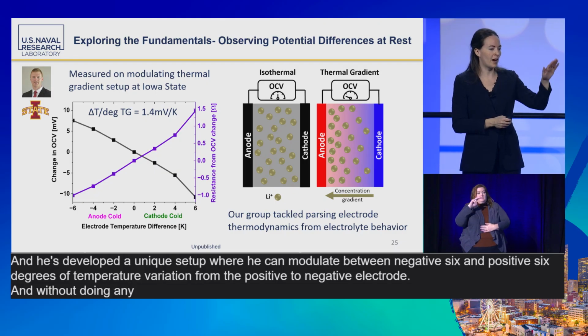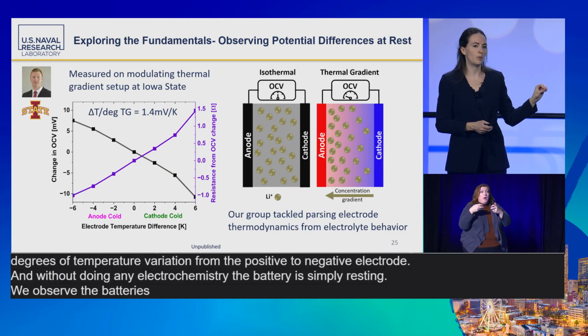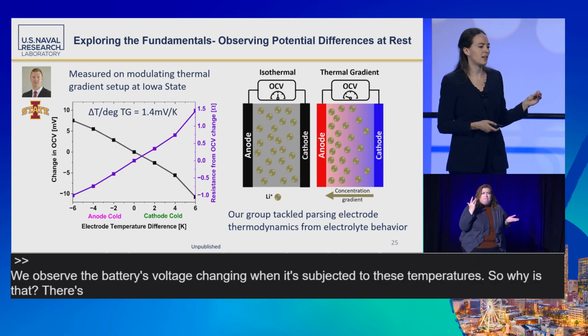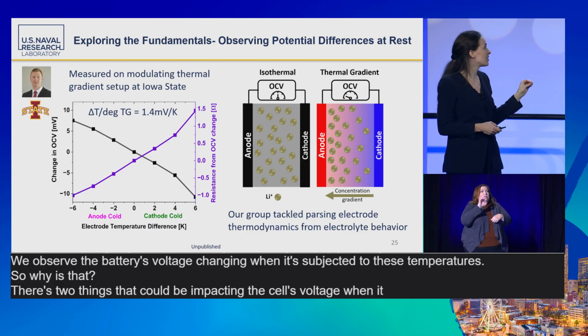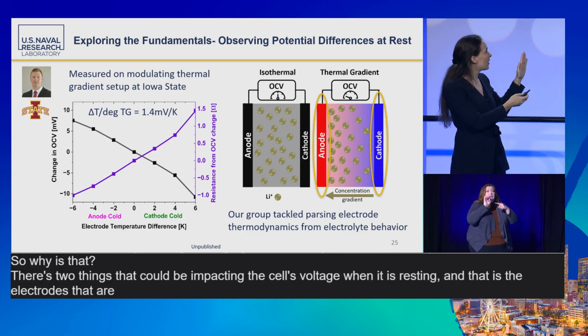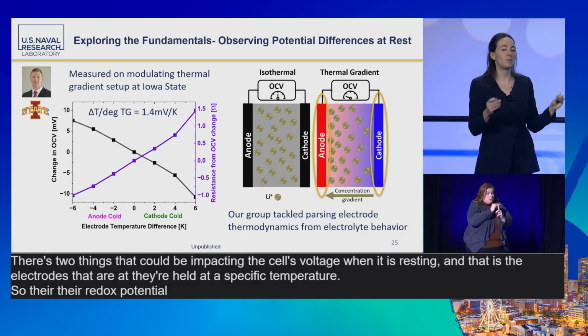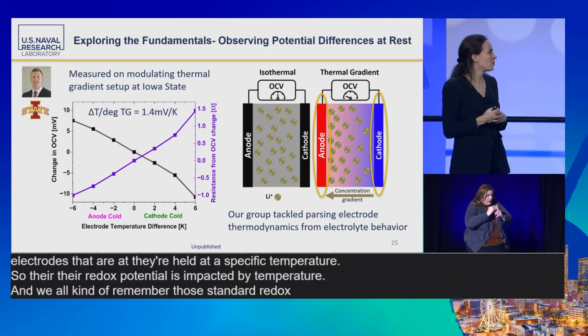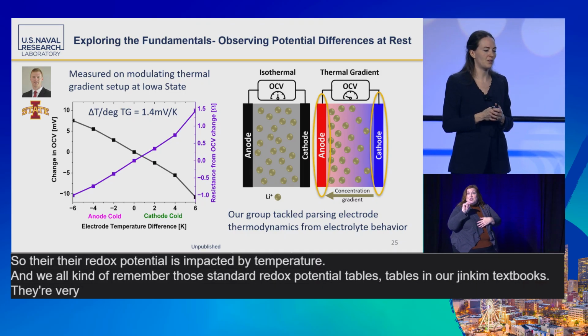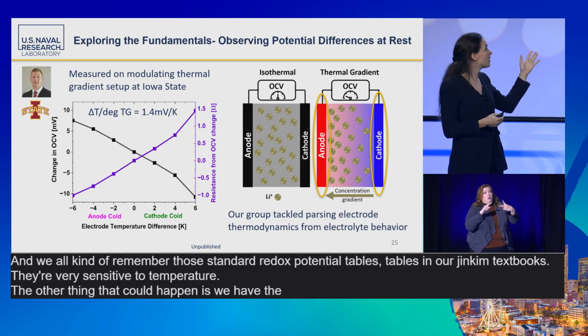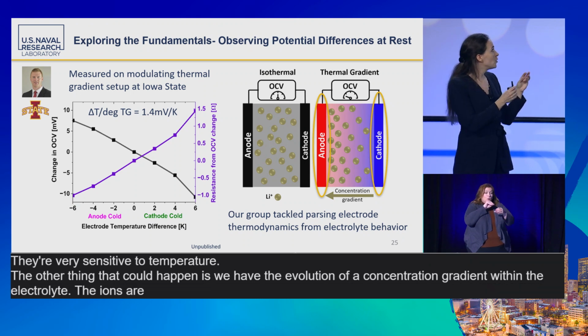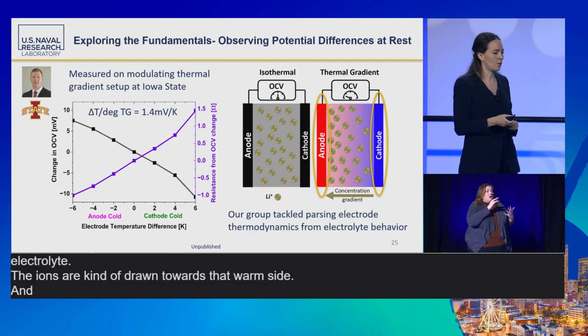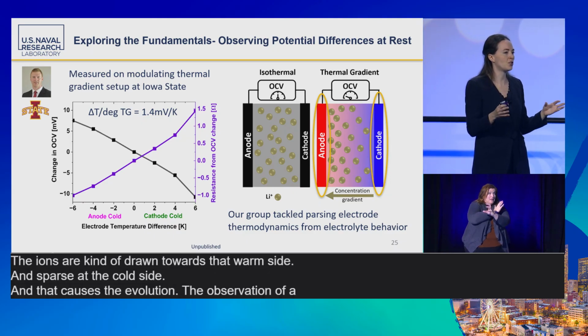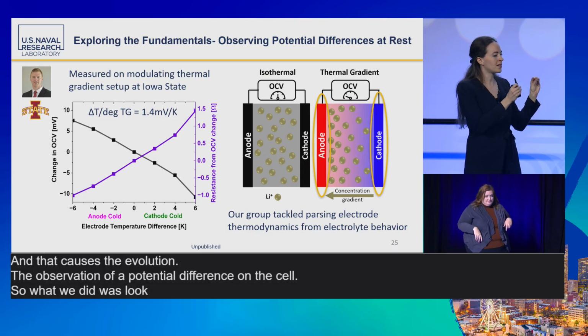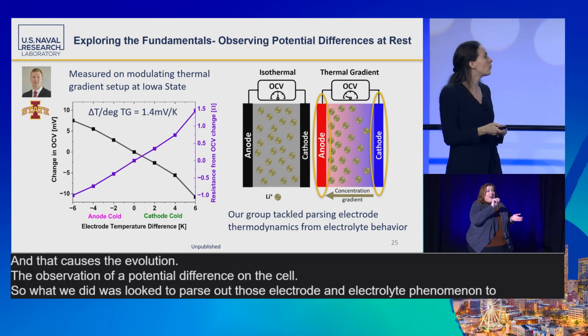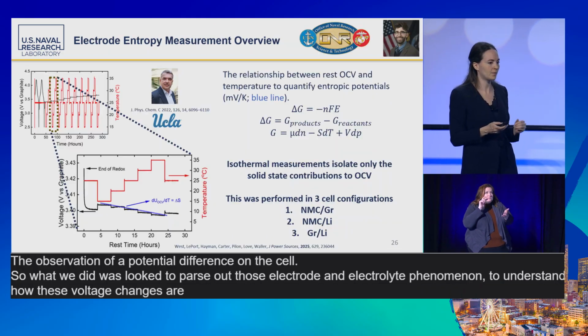And without doing any electrochemistry, the battery is simply resting. We observe the battery's voltage changing when it's subjected to these temperatures. So why is that? There's 2 things that could be impacting the cell's voltage when it is resting, and that is the electrodes that are held at a specific temperature, so their redox potential is impacted by temperature. And we all kind of remember those standard redox potential tables in our Gen Chem textbooks. They're very sensitive to temperature. The other thing that could happen is we have the evolution of a concentration gradient within the electrolyte. The ions are kind of drawn towards that warm side and sparse at the cold side, and that causes the observation of a potential difference on the cell. So what we did was look to parse out those electrode and electrolyte phenomenon to understand how these voltage changes are developing.